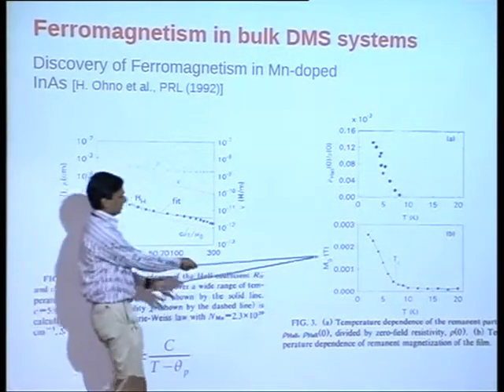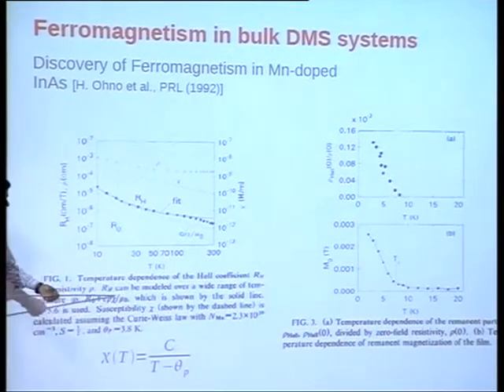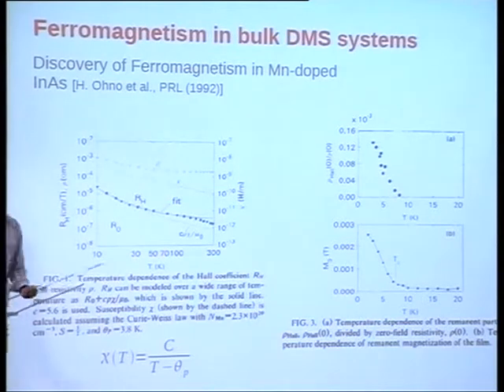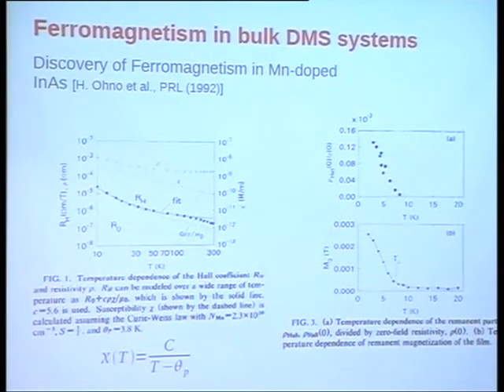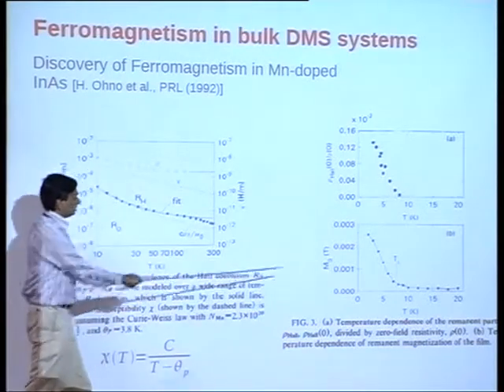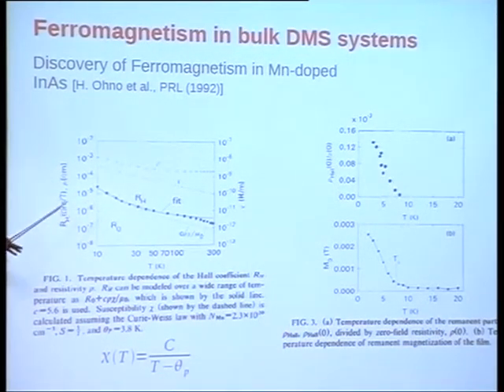Well, this is chi, yeah. I think often the samples are very small, and that causes difficulties. So suppose you have a tiny sample in a ton of other stuff, then somehow they managed to do it. I don't know the details of this one, but it was probably not easy. But most commonly, this is how it is done in mesoscopic systems. You extract it out of transport. Because your sample is probably some microns across and it's buried in a huge bulk of other stuff, and whatever magnetization measurements you do will be more or less dominated by the rest, rather than what's happening in this tiny thing very deep down.